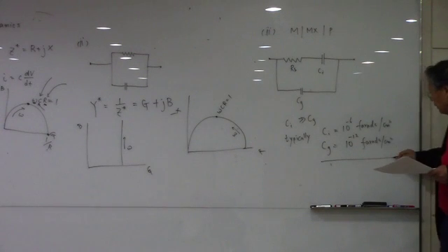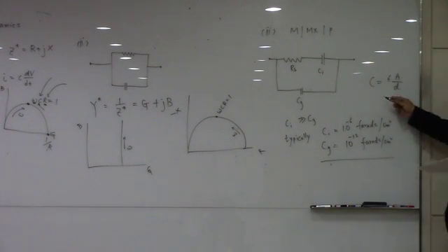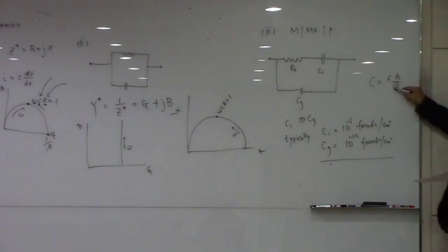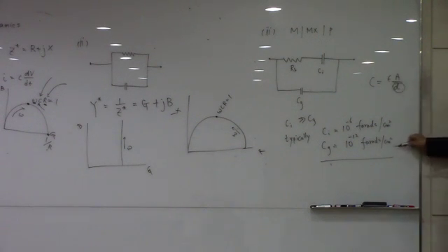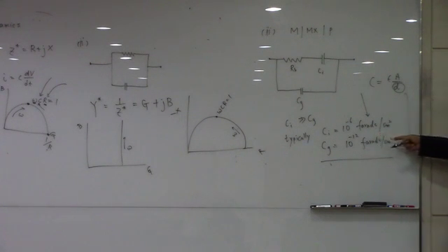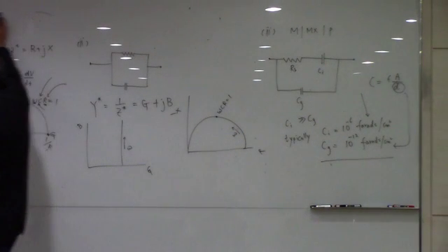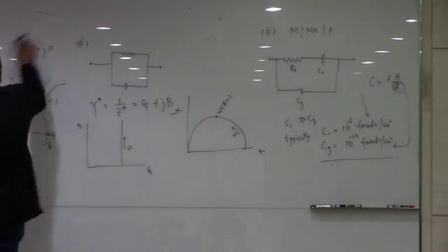And the reason is that the capacitor is something like this, right? Here, the thickness of the geometric capacitance is very large compared to the double layer due to the polarization at the electrolyte at the electrode surface. So the d is tremendously different between these, so the capacitance is going to show that much difference. Okay.